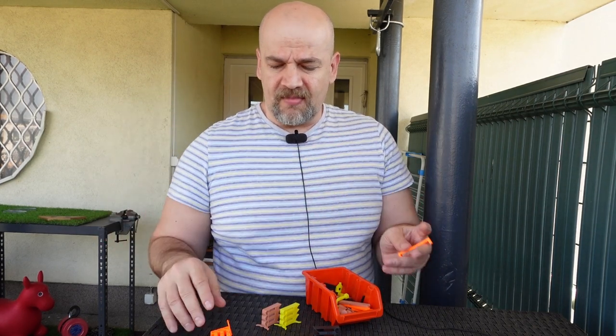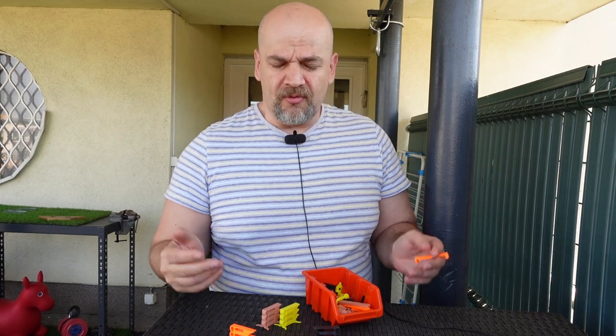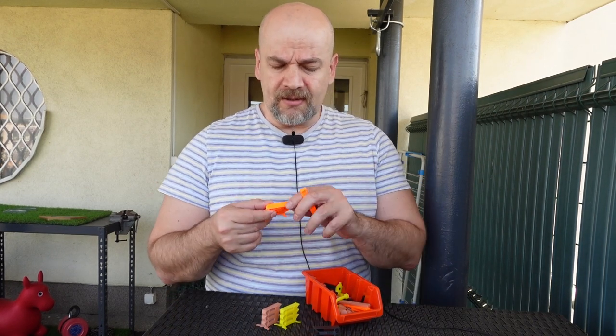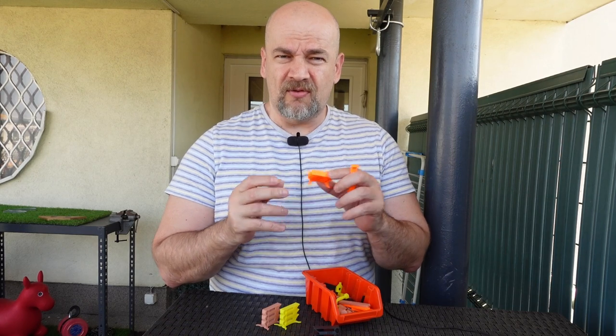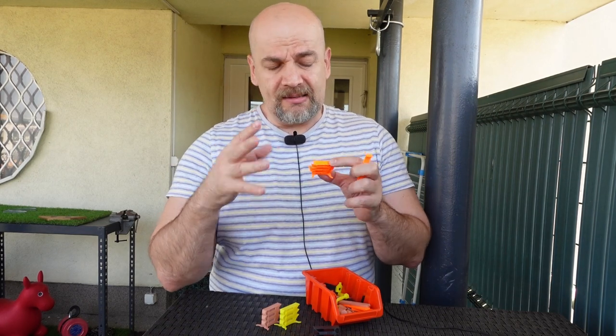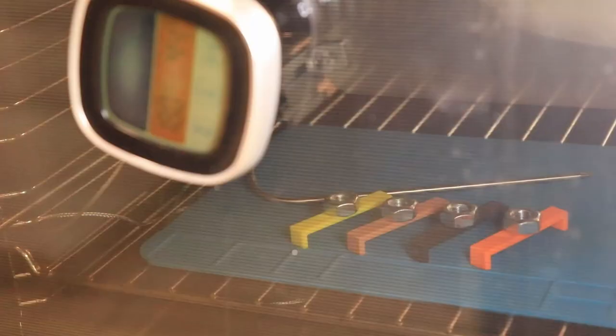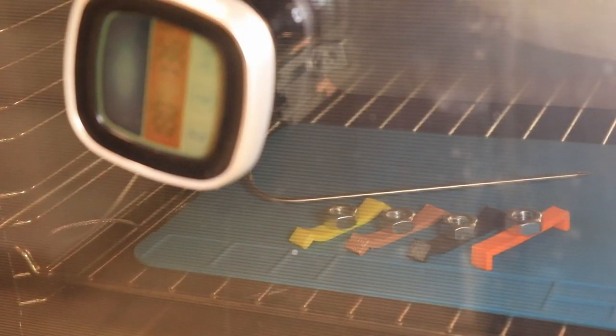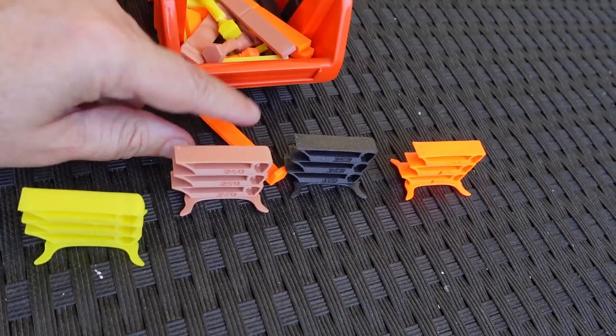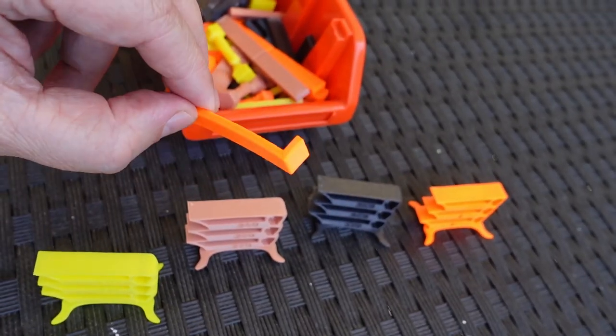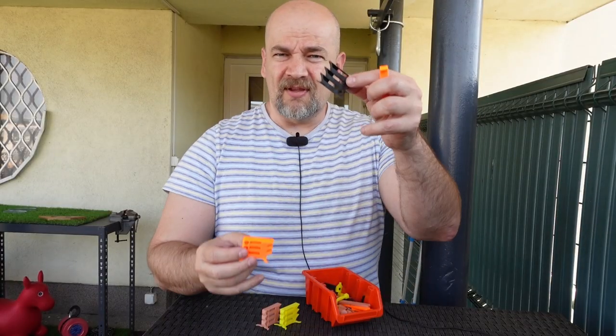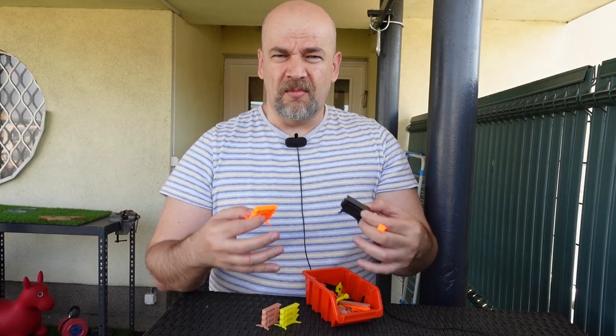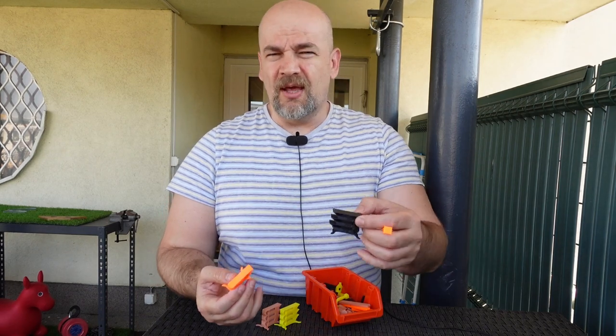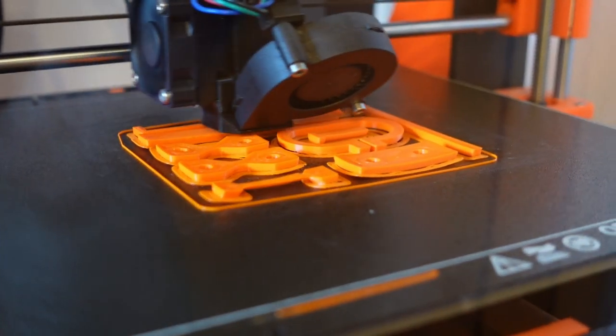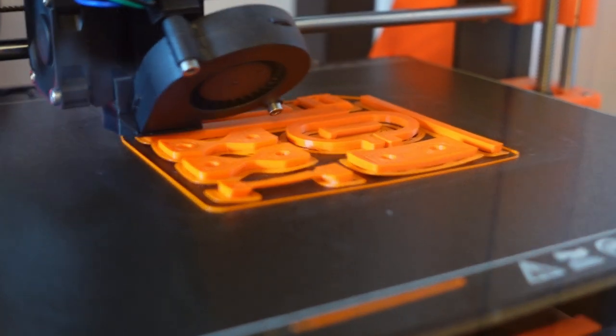And actually the next step is the PC blend, from which I was expecting a little bit more in these mechanical properties, except it was a very pleasant surprise to see that temperature test. So I tried to follow the deformation. It started at approximately 150 degrees Celsius, so that's quite incredible. But don't forget, it is not as creep resistant as ASA. So if you want to build something which will be under constant load, you still want to go with ABS or ASA. And don't forget, the PC blend is not so easily printable, so it warps a lot.